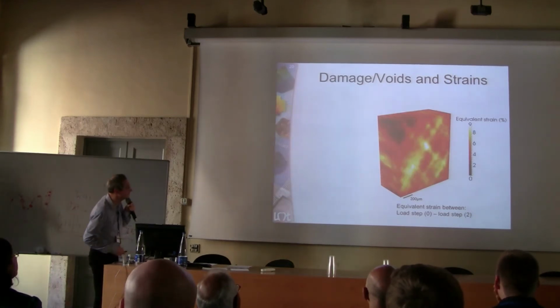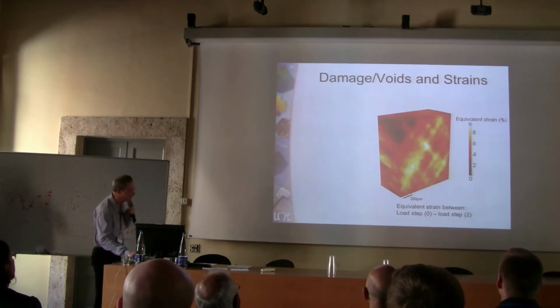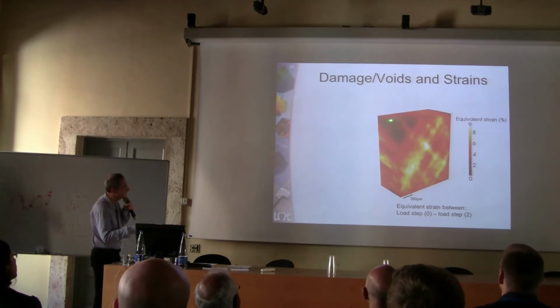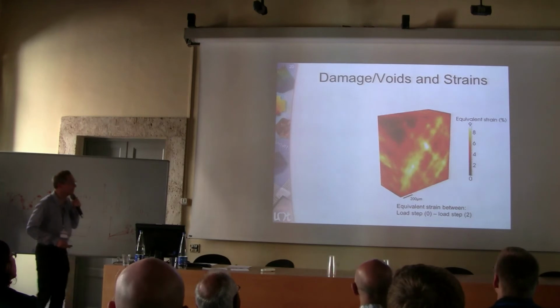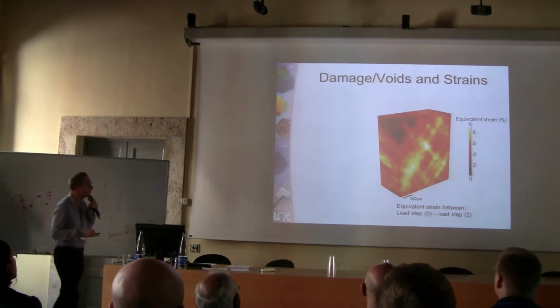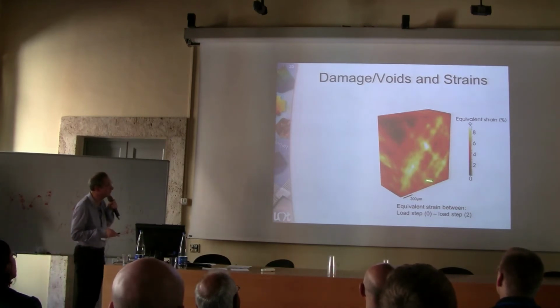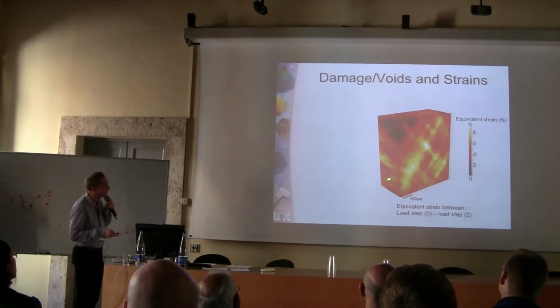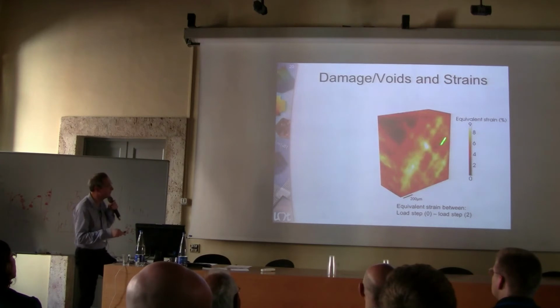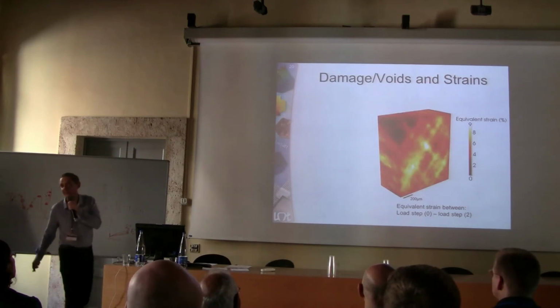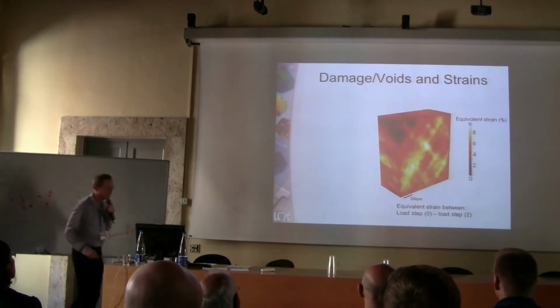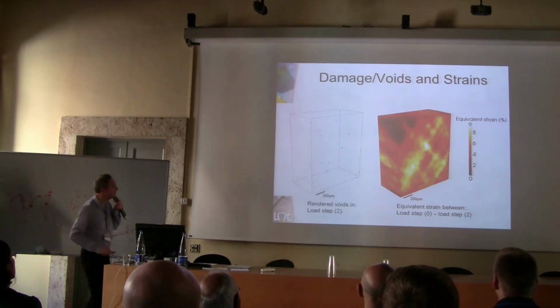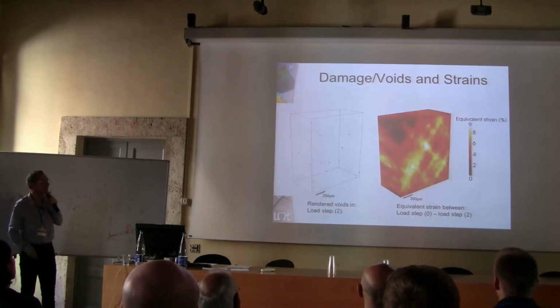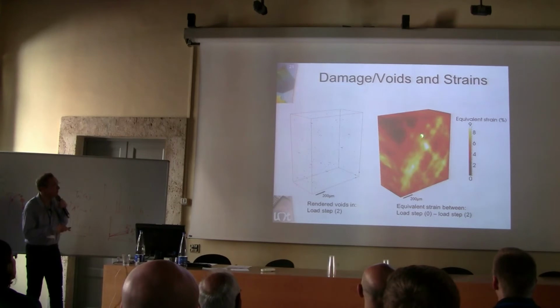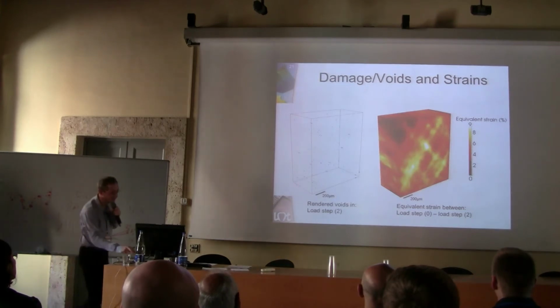Let's proceed to the second loading step. Basically, you have this X-shaped type of strain bands - I call them strain bands because of course you have lots of strains in the bands, but you still have plastic strains in the bulk too. You still see a little bit of activity, but nothing correlated to the presence of these strain bands.